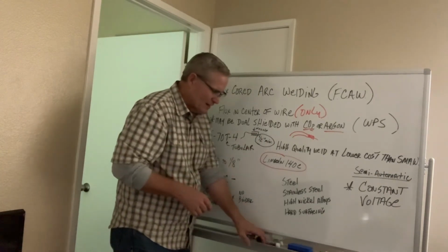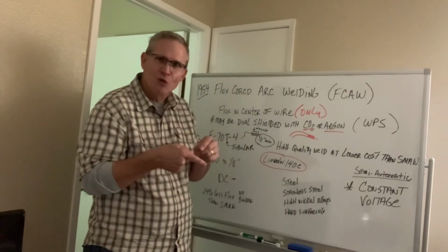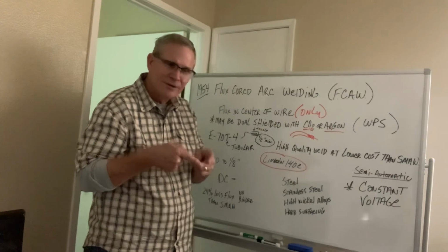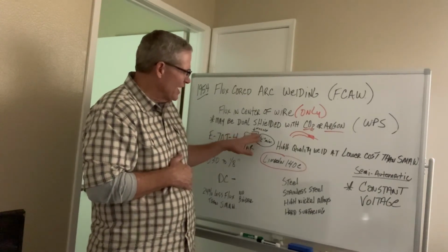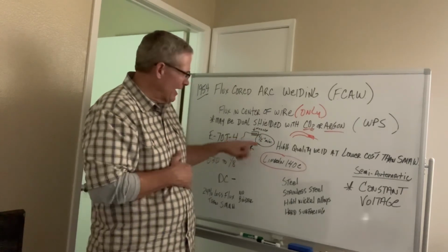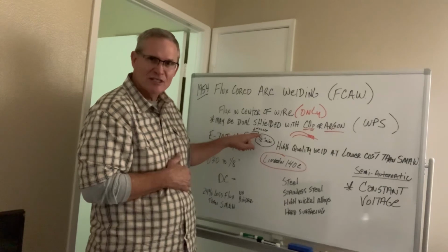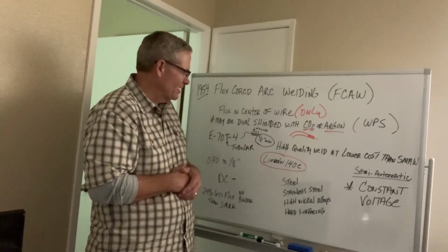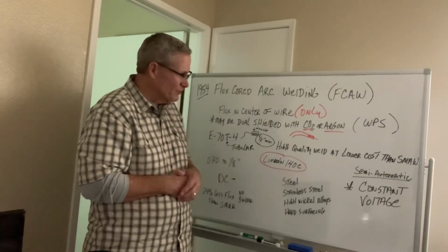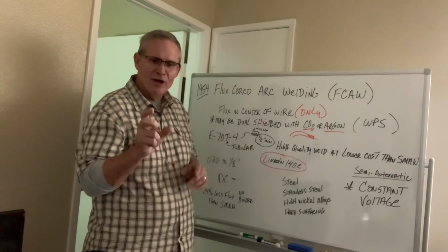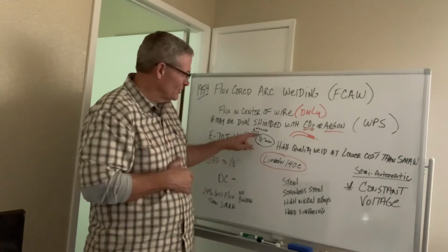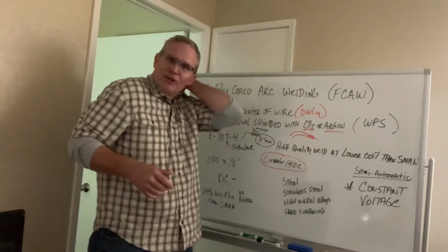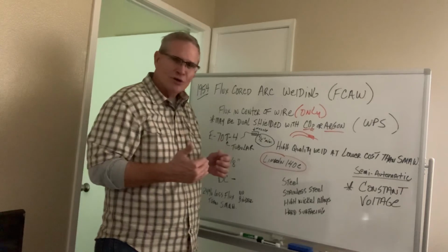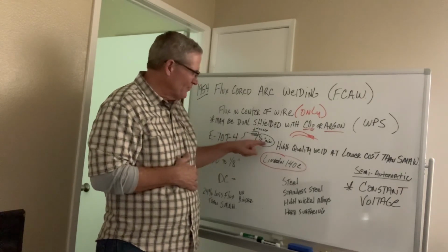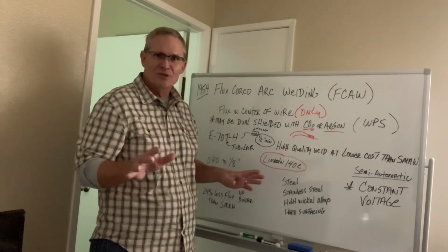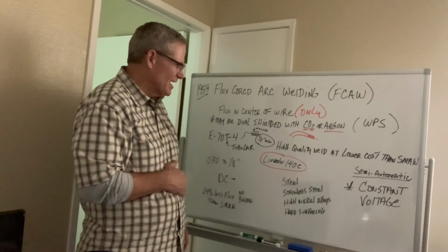So in other words, let me compare it. With MIG welding, you can get as close as you want. You can bring the nozzle right up and bring the wire right up with it. But with this process, if you bring that nozzle any closer than 1/2 inch, it will actually fry this contact tip inside the nozzle itself. So you can go through quite a few contact tips very quickly if you're not real careful with it. Some of the wires require 3/4 inch stick out. Some of them are 1 inch stick out. So what it's saying is that during the welding process, you do not want to be any closer to the weld metal itself than 1/2 inch. It's a good rule of thumb to go by, so you're not damaging this contact tip.